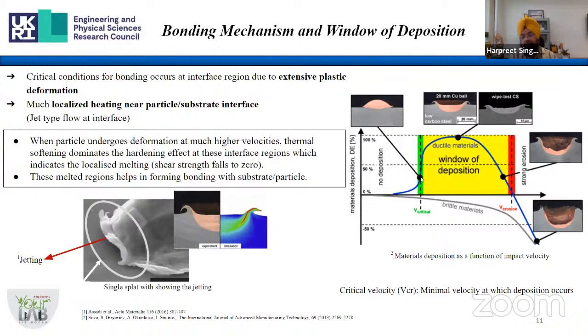So for example, in here, this is the point. And then, of course, you can increase the velocity to increase your deposition efficiency. And then there will be again an upper limit, beyond which you will see that the particles will start eroding the surface rather than sticking on the surface. So here they are rebounding, but here they are sticking on the surface. So that means our useful process window, or window of deposition as they call it, is limited by this velocity, and that is actually our job. Whenever you get a new set of feedstock material and substrate material, the first thing is to see what the critical velocity could be, and that is the whole challenge in cold spray.